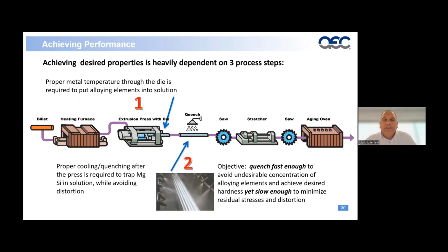The next phase, and this is what I consider one of the most complex parts of extruding a more advanced extrusion that's highly engineered relative to its chemistry and tolerances, is the proper cooling. If we want to put the magnesium silicon in solution, we want to do that as aggressively as possible with a quench, but we need to avoid distortion. So the main objective here is to quench fast to avoid undesirable concentration of alloying elements and achieve desired hardness, yet slow enough to minimize residual stresses and distortion.